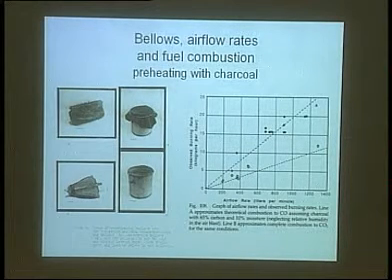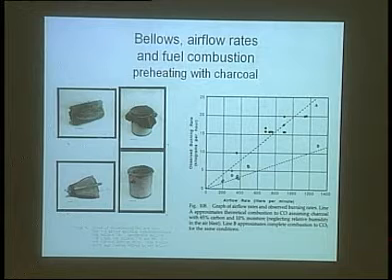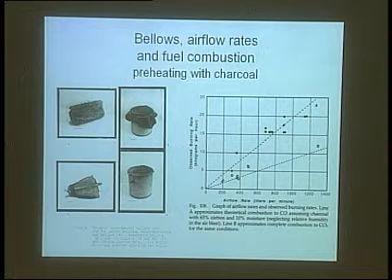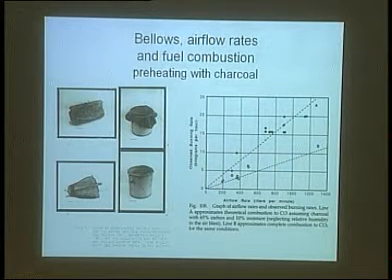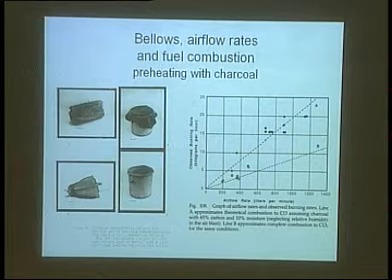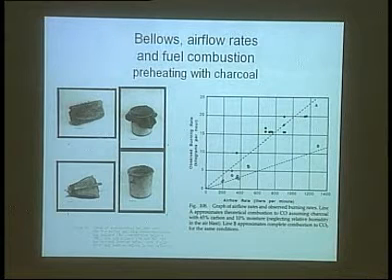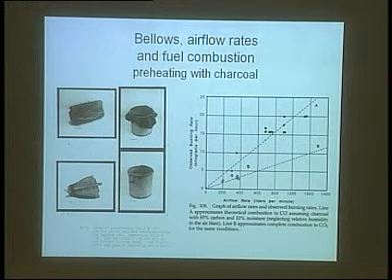And on observations, this type of bellow here, the pot bellow, was actually far superior to the bag bellows, which would represent maybe an earlier period. So this is right out of the tomb of Rekhmire. What are some of the benefits of these pot bellows? Well, the first one is that the airflow we can generate from that was much higher. Working at a good pace, stepping from one bag to the next, we could generate about 350 liters of air per minute. Okay, that's quite good.